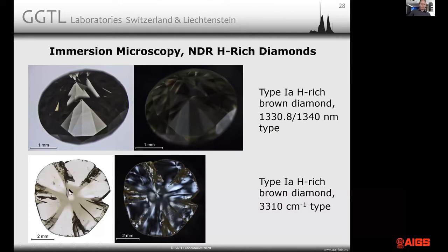It's one of those mixed cuboid octahedral stones, so-called asteroidal diamond. And the top one is just hydrogen-rich. The top one on the cross polar in immersion shows barely any color zoning. So the color is relatively homogeneous in these stones.